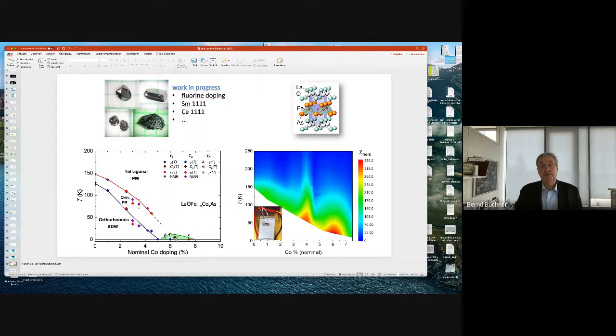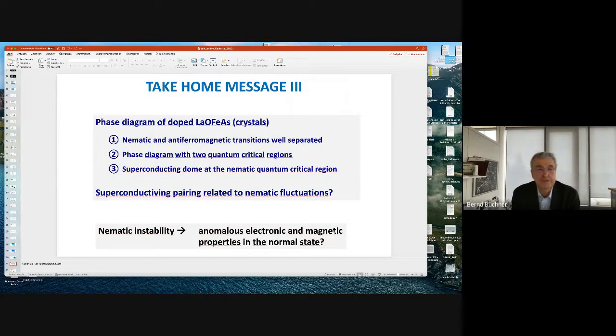So superconductivity here appears in a region in the doping range where the nematic instability becomes quantum critical, where the nematic instability becomes very large as signaled by the large susceptibility, where the nematic fluctuations are very, very large. And this is, in some sense, the take-home message 3. So for the first time, we were able to measure the phase diagram of these doped 1111 systems on single crystals. What we find is that indeed these two instabilities, the nematic instability and the magnetic instability, are well separated, not only in the parent compound by different temperatures, but also in the whole concentration range.